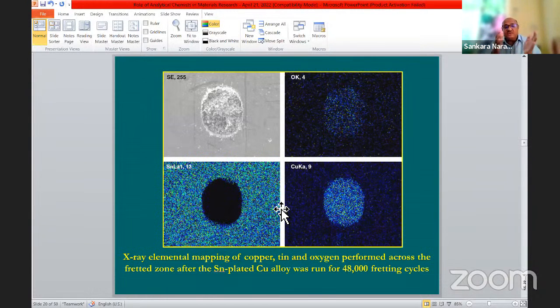We also did X-ray elemental mapping. Elemental mapping is very good to understand the mechanism. For example, this is the scanning electron micrograph. This is the fretted area. This is the damaged area. We analyzed for tin, copper, and oxygen. You can see there is a hole. There is no tin. That confirms the EDX line scanning also.